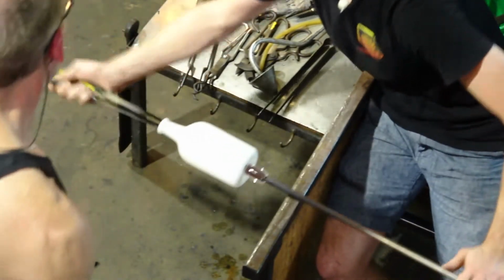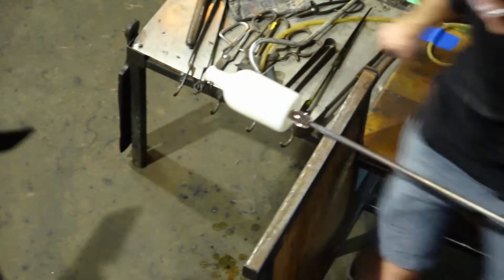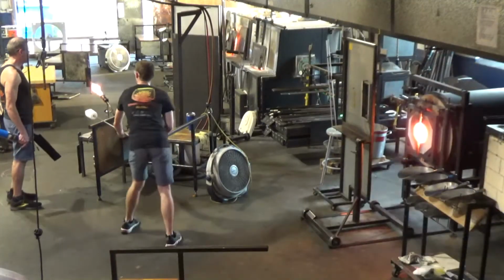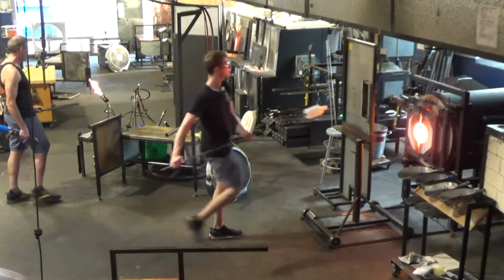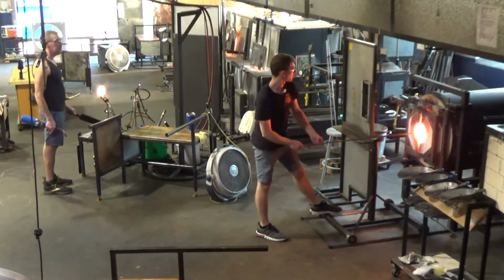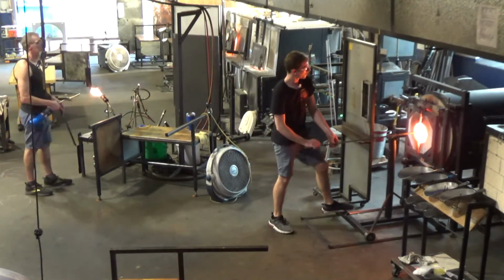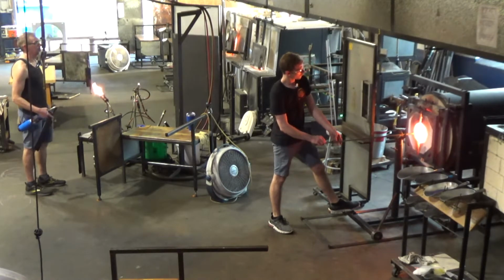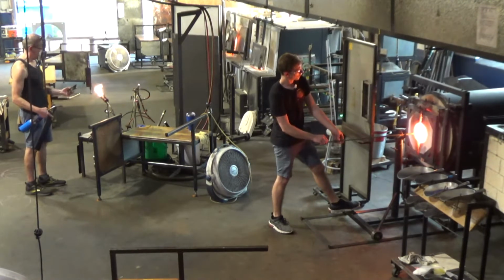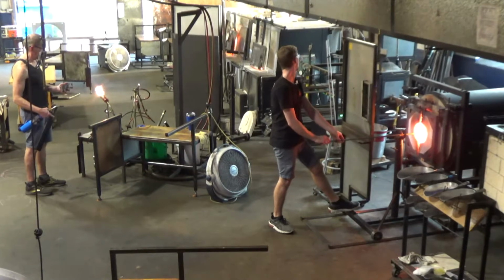But once it's finished and it's sitting around that 1,000 degrees, we can't let it get too cold. Because if the glass cools and the outside cools more quickly than the inside, then the piece will crack because it'll form stress. So what we'll do with those pieces is when they're done, we put them in our annealing ovens.